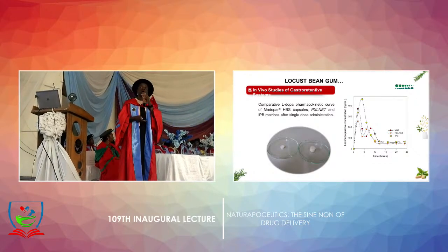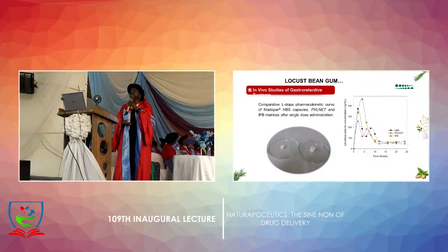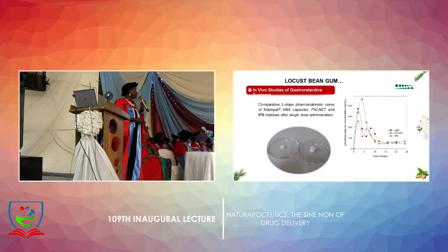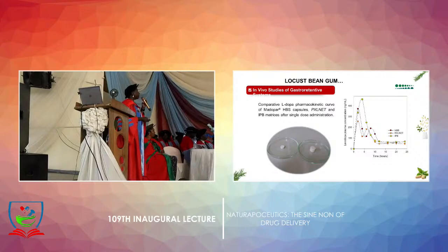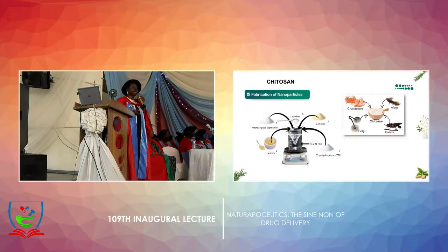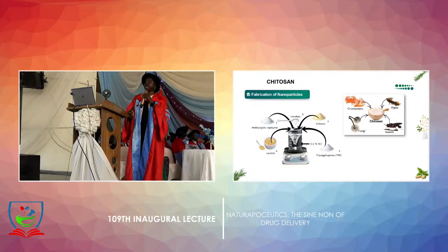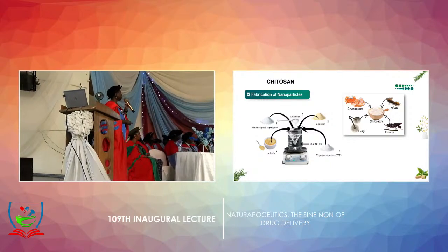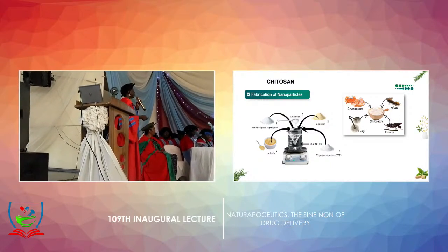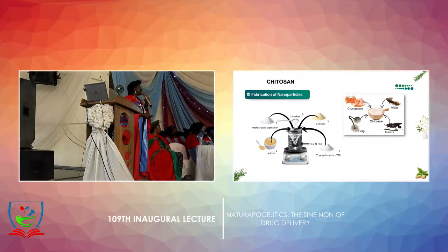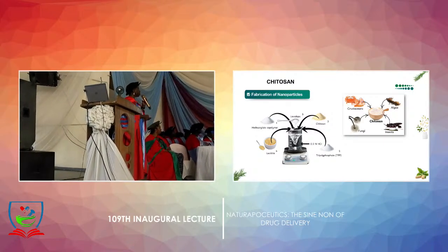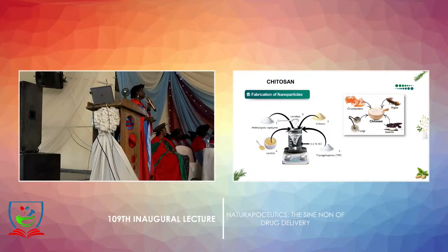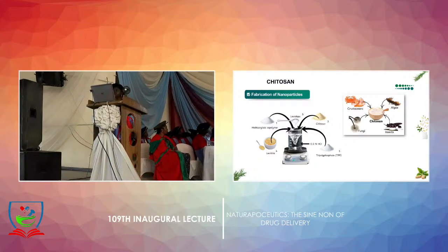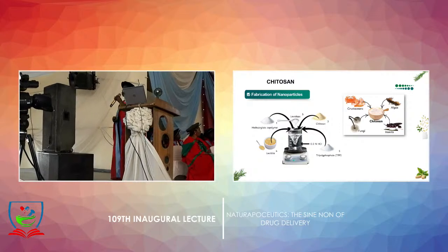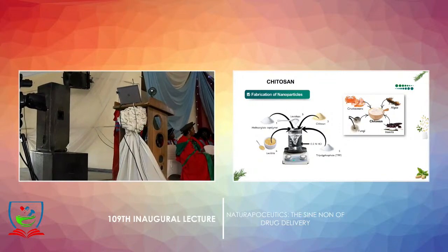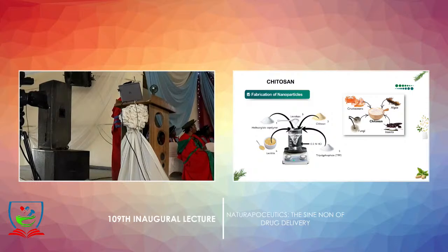So just to quickly show how we prepared the nanoparticles I was talking about. We employed chitosan. You can get chitosan from animals, and you can also get chitosan from aquatic plants. So what we did, we had our methacrylate copolymer, and then we also had chitosan. I will explain further as we go on. And then we had lecithin and tripolyphosphate. We used this to achieve cross-linking. So when we did that, we were able to get our nanoparticles nice and cute, spherical as they are.